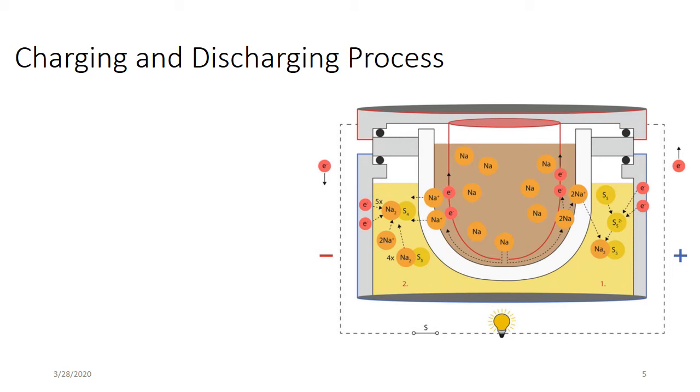The figure in the right side is representing the discharging process, where a lamp load is connected to the terminals of the sodium-sulfur cell. The low electrochemical self-discharge is typical of sodium-sulfur cells. The battery self-discharges only over very long storage periods. But to maintain a 20 kWh battery at operating temperatures, around 100 Watt of heating capacity is required. This phenomenon is called thermal self-discharge. If this is included in the electrochemical self-discharge, then the self-discharge is actually very high.